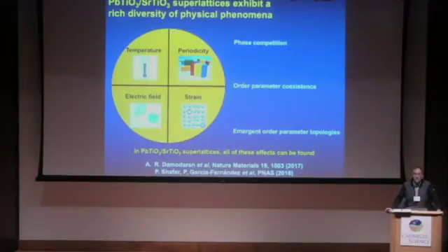So in this particular sense, lead titanate, strontium titanate superlattices is a very sensible material to look at. This is a fascinating material. Whatever you do in this system is interesting. The reason for this is the very close competition between different orders here. So if we look at the bulk level, at the lead titanate, there are two phases that compete.